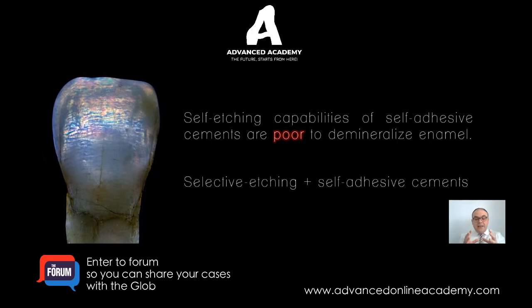Let me recap that. If I have RelyX Unicem, it's a self-adhesive cement. It doesn't come with an adhesive system. I'm going to squirt it into my crown preparation or onlay, and then I'm going to place it on the tooth structure. The self-etching adhesive is going to work well with the dentin, but not very well with the enamel. Therefore, before using the cement, I'm going to do selective etching of the enamel, and then I'm going to use the cement.